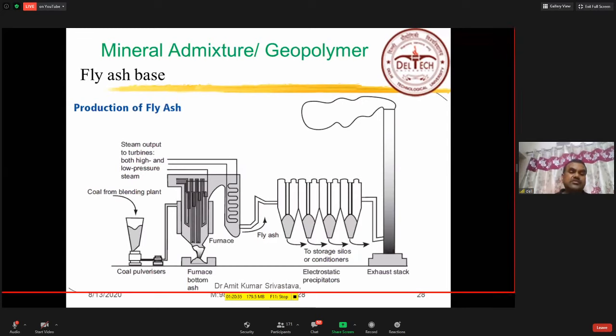This fly ash, whatever we are getting after burning in the furnace at about 1200 to 1300 degrees centigrade during power generation, has a very high source of silica. So this fly ash is very good for concrete. Now you see what happens. Here coal is there, the furnace is there, here it is burned, and after burning, the larger size particles get arrested here, and the finer particles move from here. It is the electrostatic precipitators where they are brought down, and that is called fly ash.